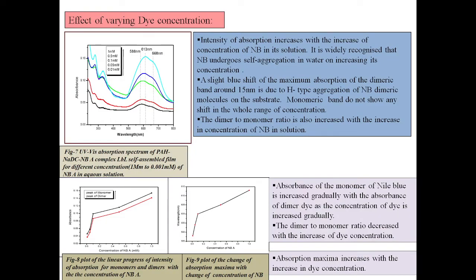Now we discuss how the concentration of dye affects the film. The intensity of absorption increases with the increase of concentration of NB in its solution. It is widely recognized that NB undergoes self-association in water on increasing its concentration. A slight blue shift of the maximum absorption of the dimeric band, around 15 nm, is due to H-type aggregation of NB dimeric molecules on the substrate. The monomeric band does not show any shift in the whole range of concentration. The dimer to monomer ratio is also increased with the increase in concentration of NB in solution.